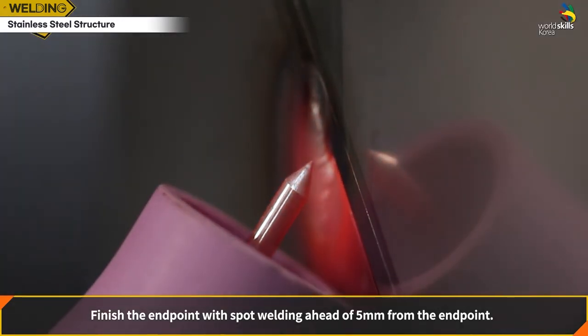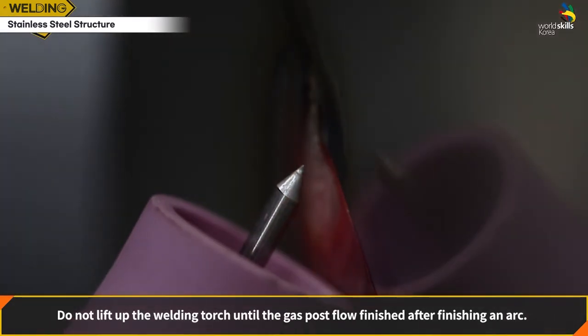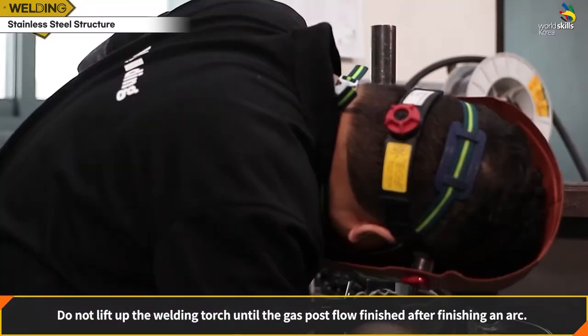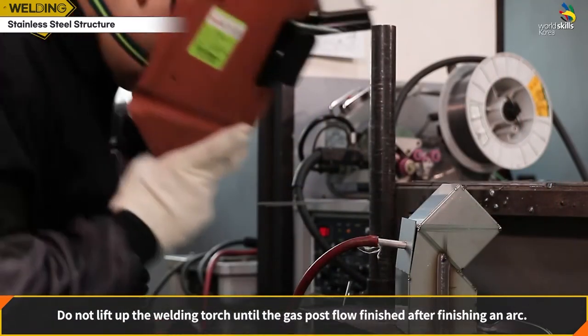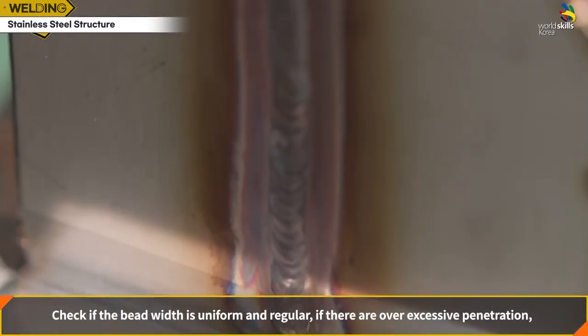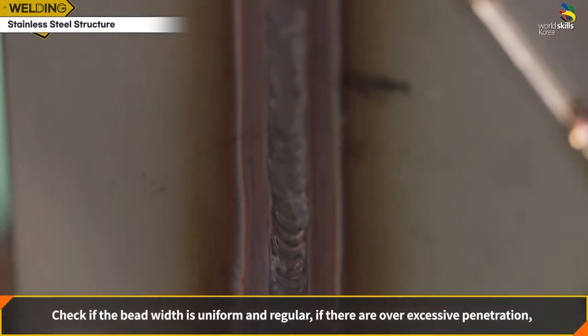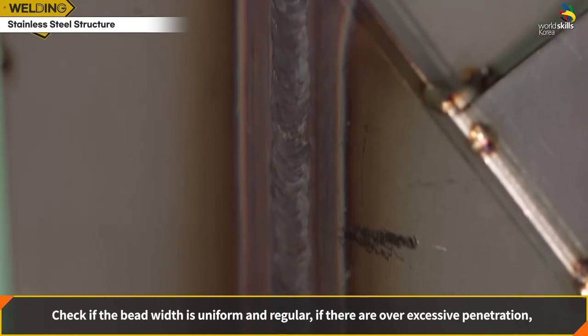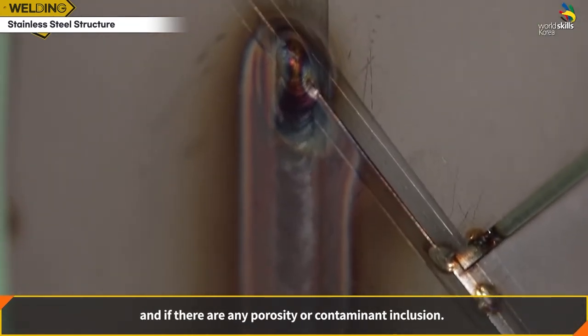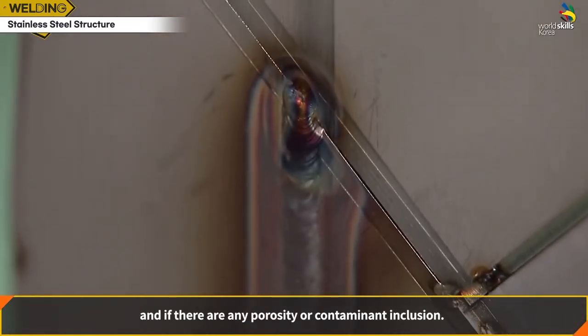Finish the endpoint with spot welding 5 mm ahead of the endpoint. Do not lift up the welding torch until the gas post flow has finished after finishing the arc. Check if the bead width is uniform and regular, if there is excessive penetration, and if there is any porosity or contaminant inclusion.